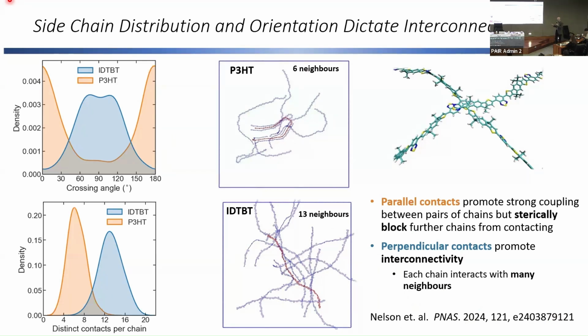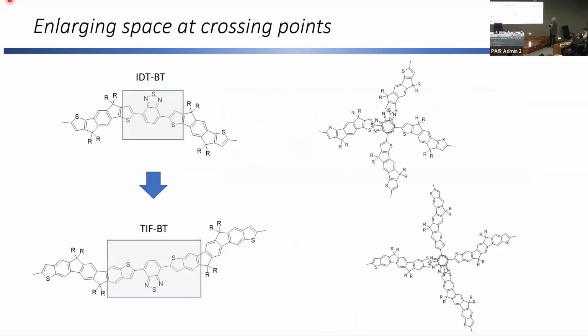And what's come out of this work is that to maximize the charge transport in a semiconducting polymer, you really don't want to have parallel contacts, because the parallel contacts sterically block a lot of interactions. Whereas if you have perpendicular contacts, for the same length of chain, you have a lot more connection to other chains. And it's a combination of having a very planar, low energetic disorder backbone and lots of contacts. That's the key message for being able to have high transport properties.